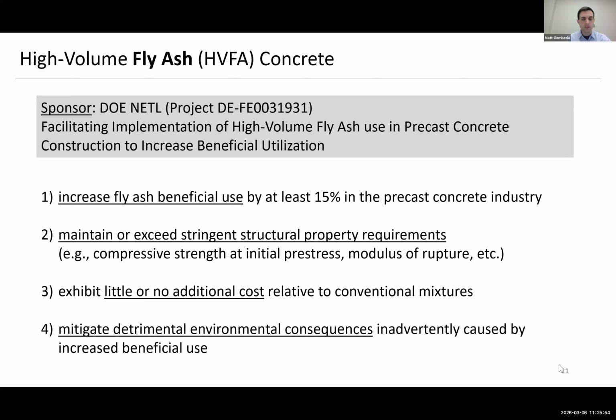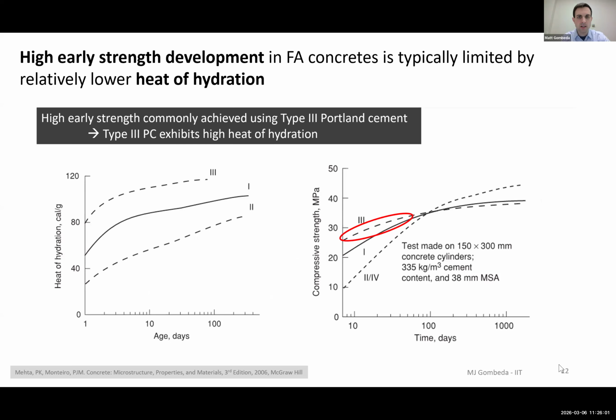And we wanted to change that narrative and find other ways to get the early strength even with more fly ash. You could kind of see here an example where typically, we're using type 3 cement traditionally in precast mixes, and you get that really high rapid strength gain early on. But when you start to replace that type 3 with larger volumes of fly ash, you start to get lower strength gains. Like you see that curve down below, the curve is going to be similar more to what you would see in like an old school type 2 or 1-2 cement at higher dosages.